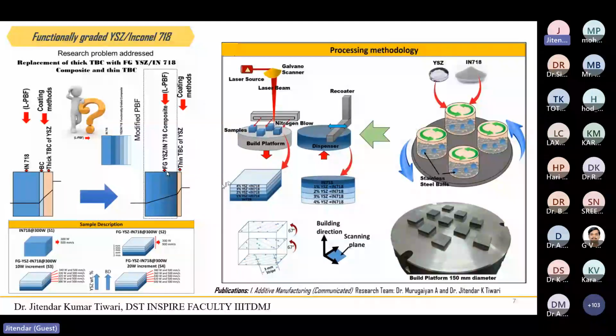So the question is how we can achieve functional gradation in existing LPBF systems. Although I would say this is not the standard method to make functionally graded material, because we have to mix the powder separately, and then in the dispenser we have to fill different batches of the powder manually, and then spread it on the build platform, and that's how we can achieve this kind of functional gradation.